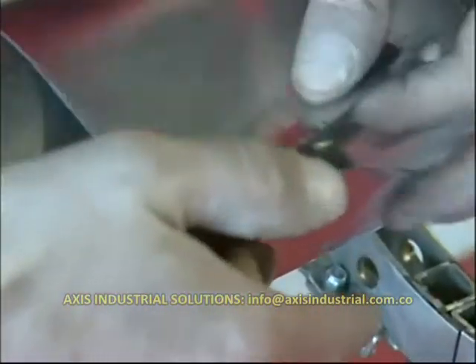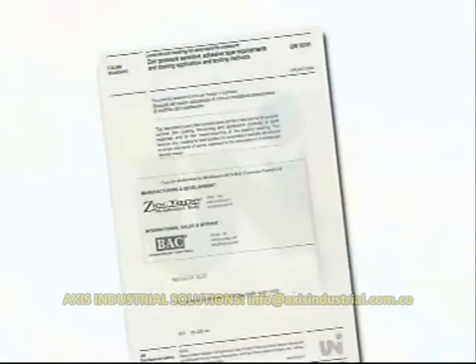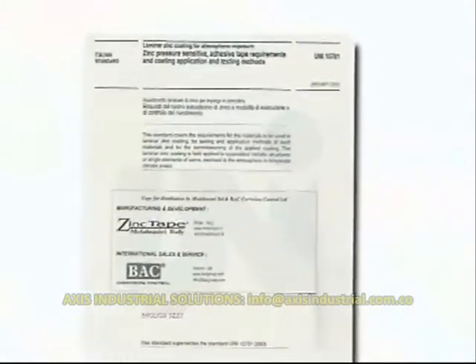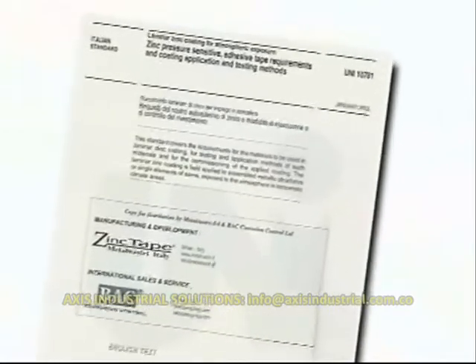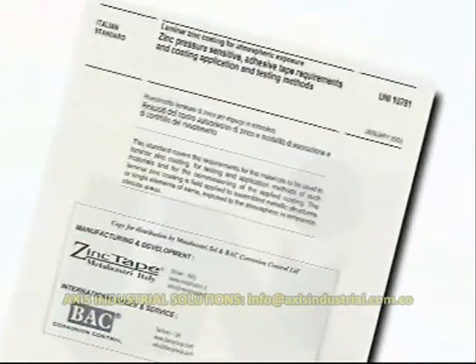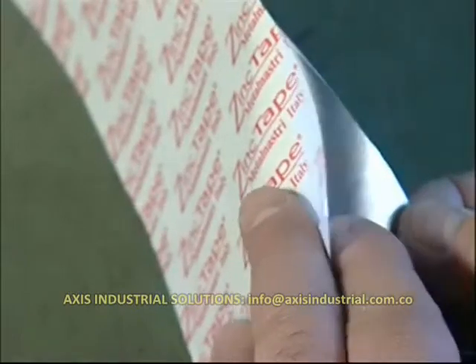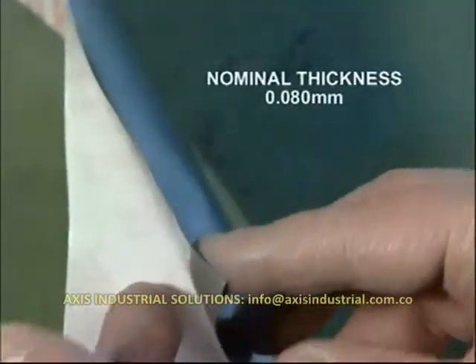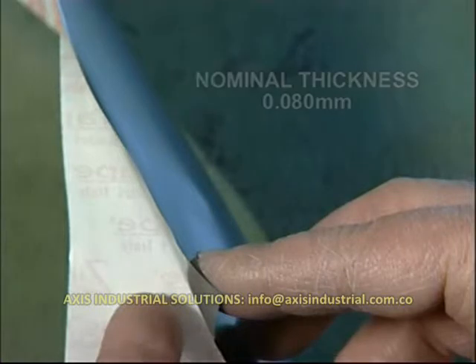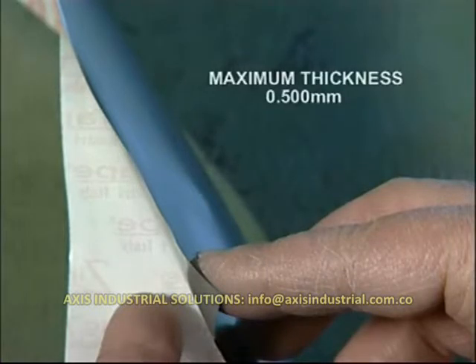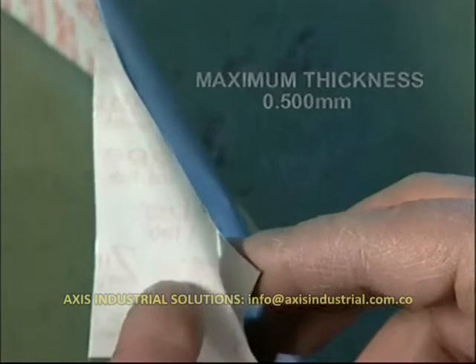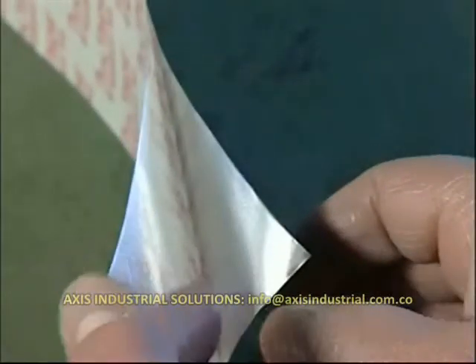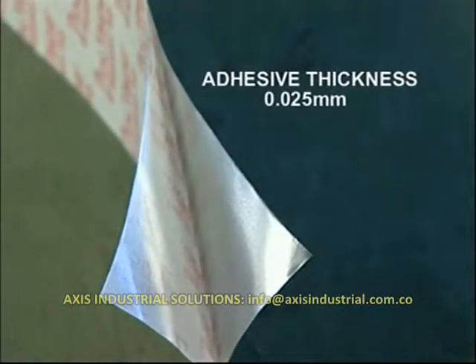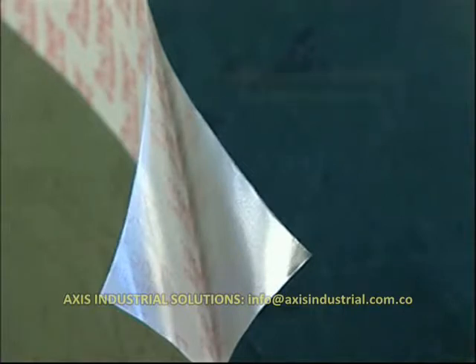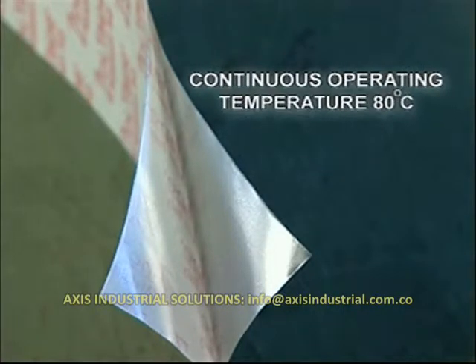and the substrate. Zinc tape is approved by the Italian Standards Institute and is covered by UNI 10781, laminar zinc coating for atmospheric corrosion. The product consists of a high-purity zinc tape with a nominal thickness of 0.08 mm, but can be supplied to a maximum thickness of 0.5 mm. The tape is supplied with an adhesive of a nominal thickness of 0.025 mm that can resist a continuous operating temperature of 80 degrees Celsius and which is a pressure-sensitive adhesive.